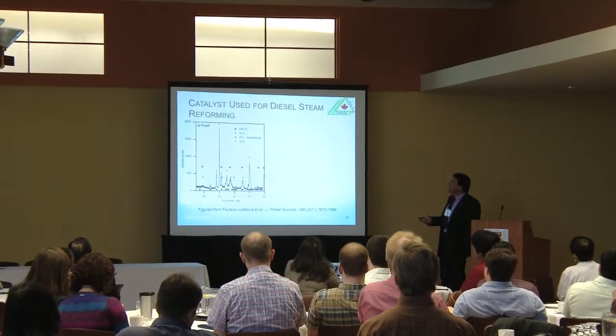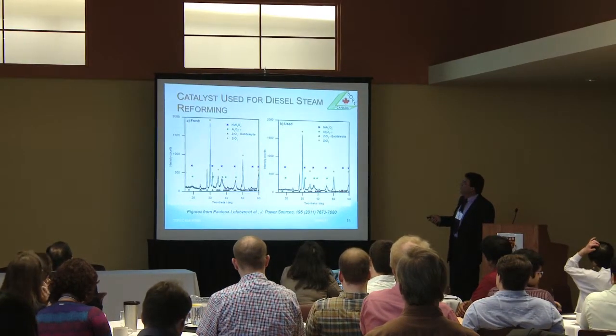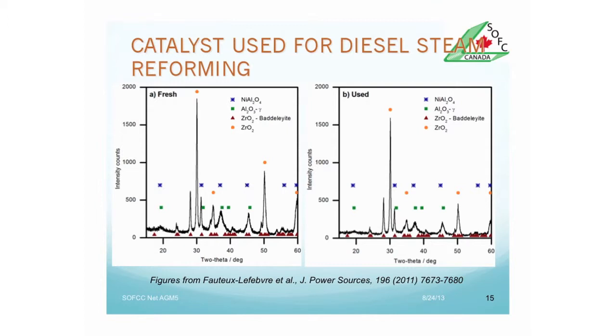So if we test the catalyst before and after, we can clearly see that there is no nickel, no nickel oxide, there is only the spinel phase deposited on alumina and zirconia. You see that there are 2 types of zirconias. This is a big, big topic. The continuation of my work is essentially there.